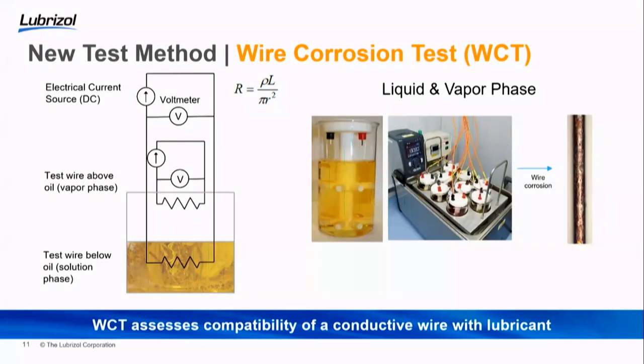And one of the new test methods that has been developed at Lubrizol is the wire corrosion test. And here it's a much more objective test, and there are some pictures there. The copper wire will sit in the fluid, but also in the vapor phase, as an electric current is passed through that wire. And the wire corrosion test assesses the compatibility of that conductive wire with the lubricant in both the liquid and the vapor phase. And that's done by measuring the resistivity of those wires.